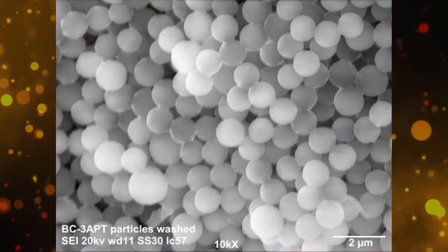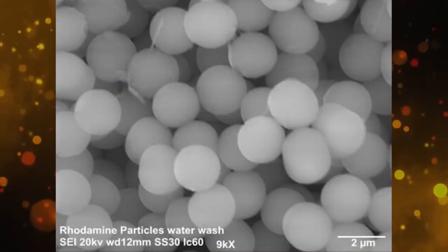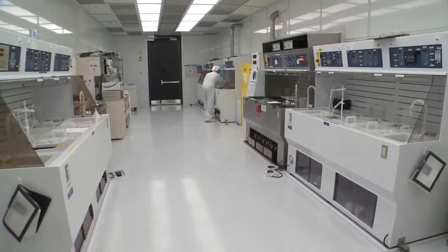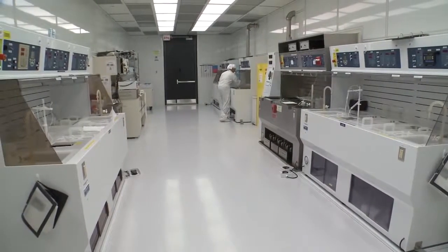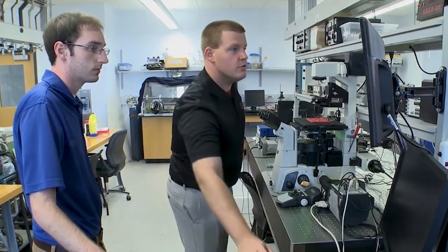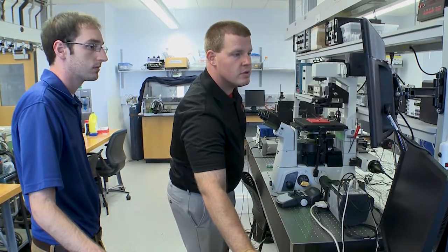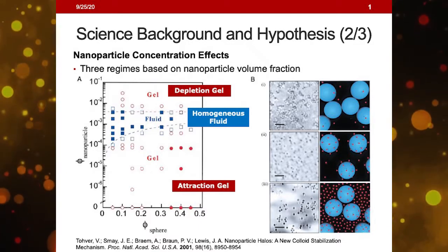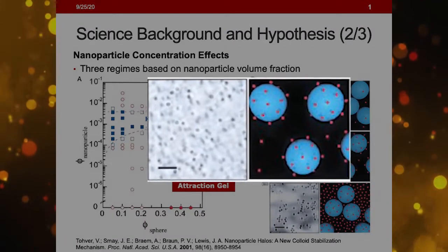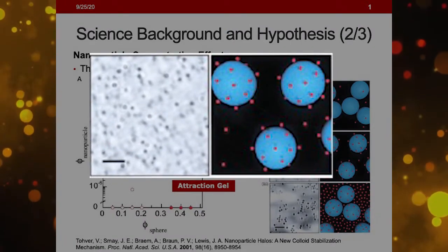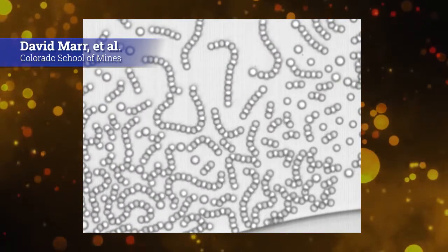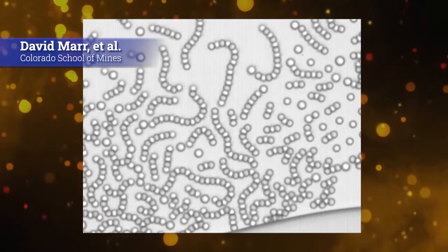With colloid manipulation, when you apply an external field, whether that field is gravitational effects, electric fields, temperature, magnetic fields, with all of these manipulation techniques, you can, in theory, manipulate not only the crystallinity of these colloids, but also the spacing between them. And if you can dynamically manipulate these particles in their spacing, you can control, for example, optical properties, whether they manipulate light in a certain direction or they're selected to a certain wavelength of light. You can manipulate their mechanical properties and also their thermal properties. Now you have a dynamically tunable material that could be used for a variety of applications.